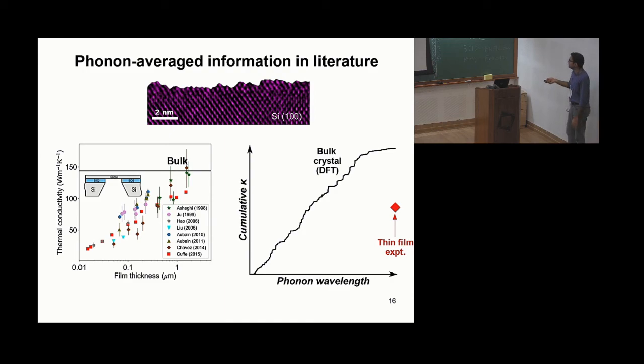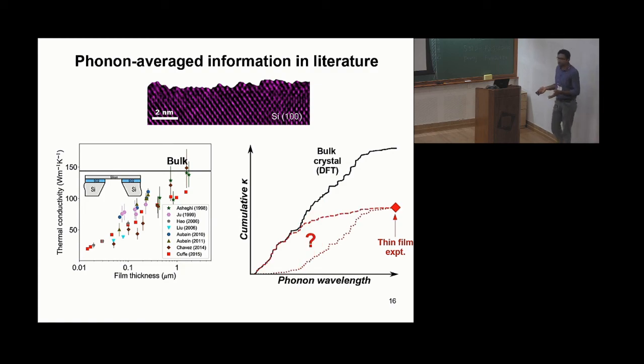You can clearly see that this red point here can be reached in this route where only long wavelength phonons are preferentially scattered at the boundary and their contribution is reduced. Or you can go in the other route where preferentially short wavelength phonons are getting scattered at the boundary and their contribution is reduced. So which of these is the correct curve? That information is not available from this kind of data set.